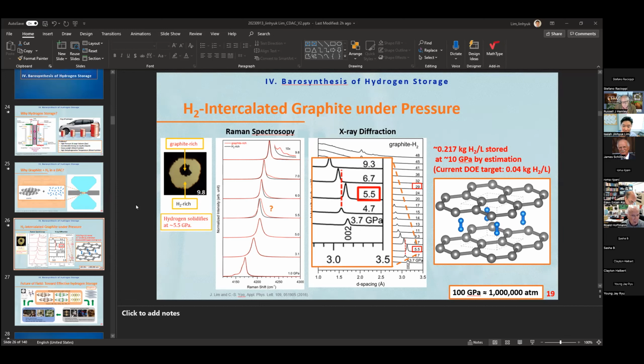Right. Couldn't you maybe repeat the same experiment with helium, which has a hydrostatic limit up to 40 GPa, and should probably penetrate graphite more easily than hydrogen? In the solid case, the distance between two hydrogen molecules gets smaller compared with the gas hydrogen. I think at some pressure it fits with the graphitic layer distance. That's also another explanation: the solidifying hydrogen can be stored in the graphitic layer space. Okay. Thank you so much.